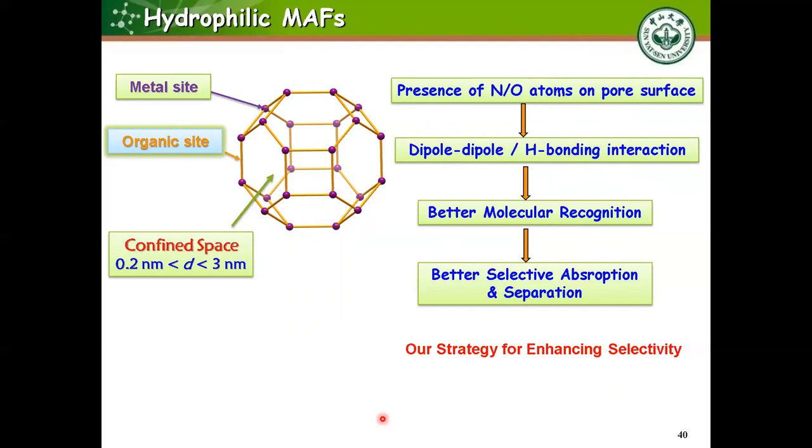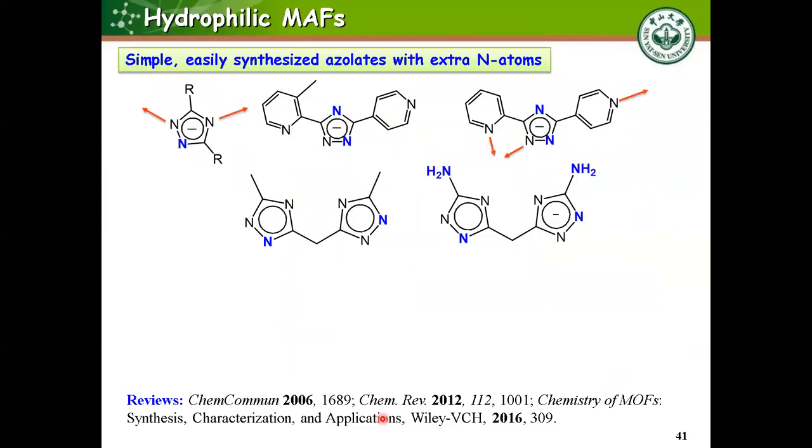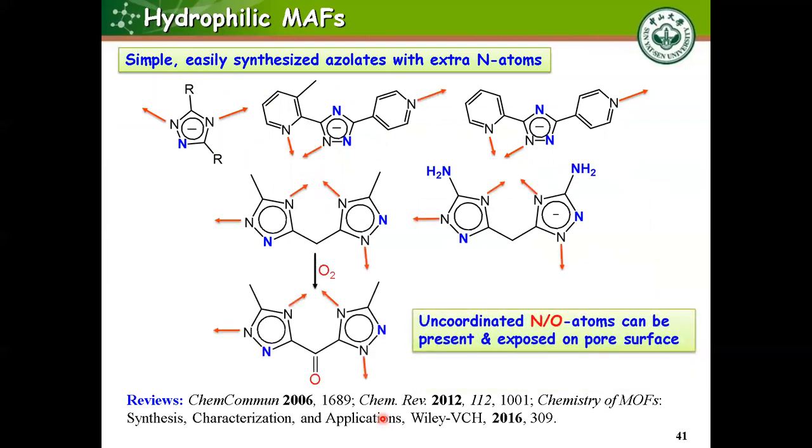Therefore, we propose another strategy using hydrophilic MAFs to enhance the host-gas interactions, even though the small hydrocarbons are hydrophobic. Our strategy is to use mono- or ditriazolate to generate micropolar MAFs. This MAF may have extra naked nitrogen atoms exposed on the pore surface for stronger supramolecular interaction to enhance molecular recognition and therefore have a better selectivity in the absorption.